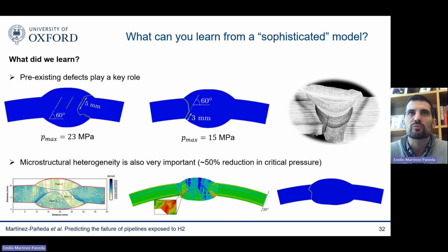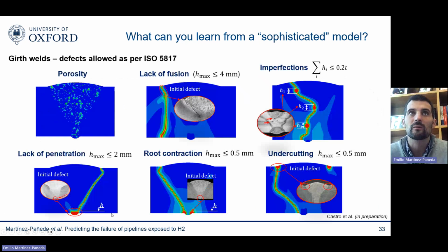And this is problematic, of course, because these are some of the pressures that have been discussed to transport hydrogen, and we know that this type of flaw exists in those natural gas pipelines. And again, you can test the role of microstructural heterogeneity, and we can see a very significant reduction in critical pressure. So this matters. This has been neglected, but this matters quite a lot.